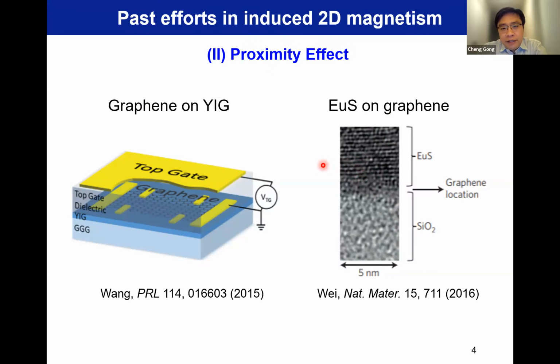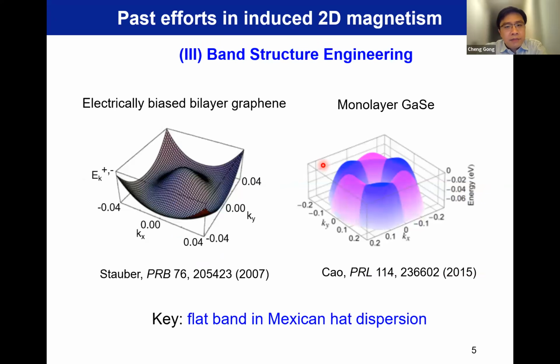The third idea is very smart. By finding materials that have a flat band, you can have a large density of states within a very narrow energy window. That can cause the so-called Stoner instability. That's why in some elemental metals we found long-range magnetic order. It's very hard to find this kind of insulator. So for example, in electrically biased bilayer graphene, you can open a small gap and then have a flat Mexican-hat band here, or highly p-doped gallium selenide. But anyhow, it's not easy to really get those materials and exactly prove that region.